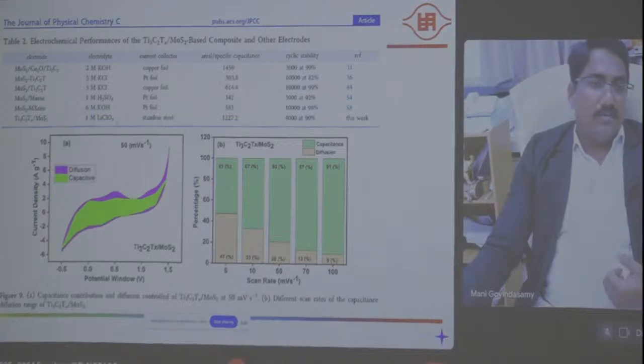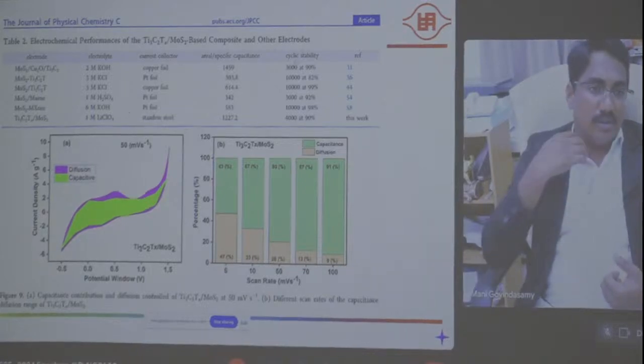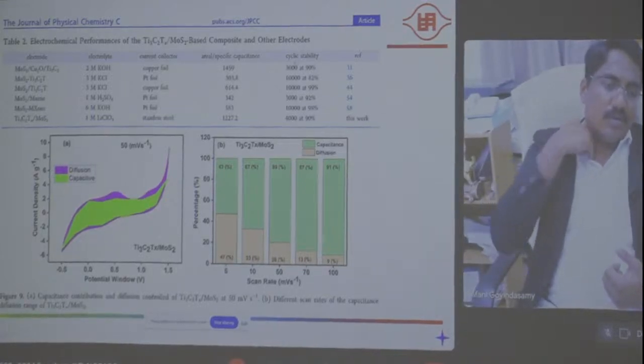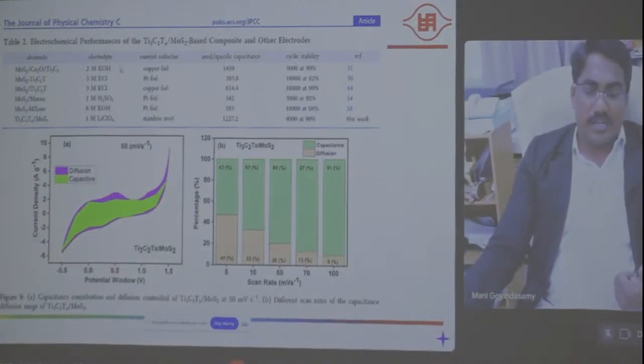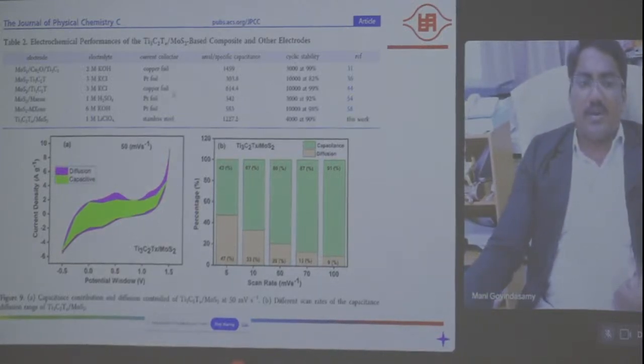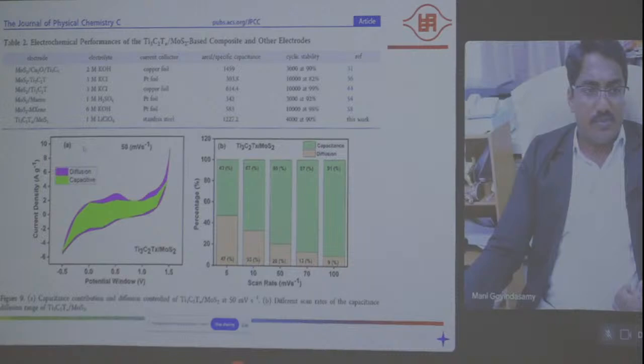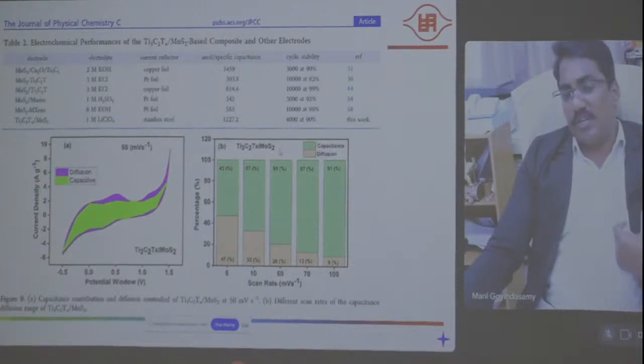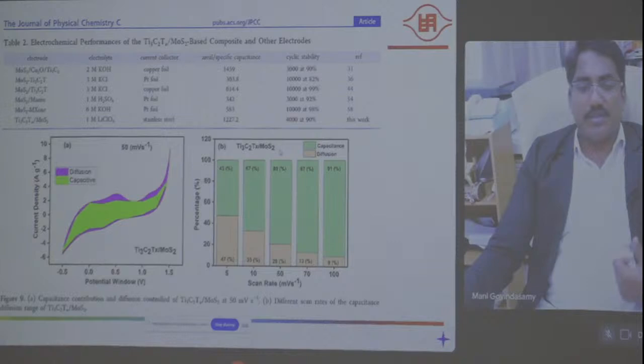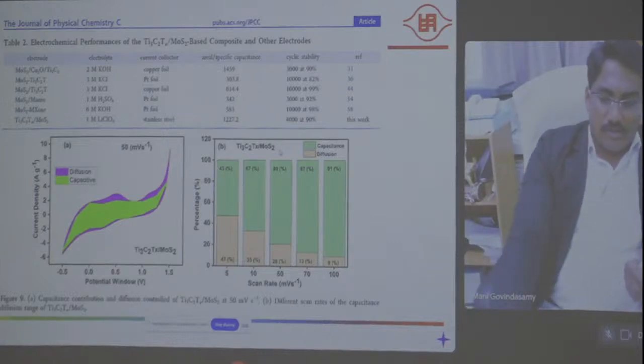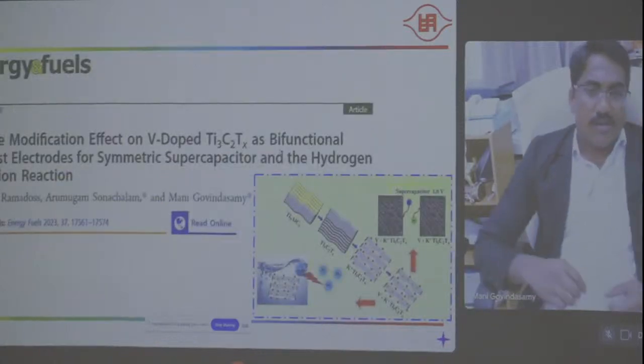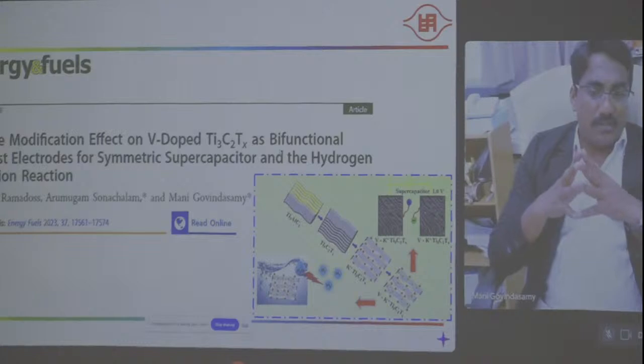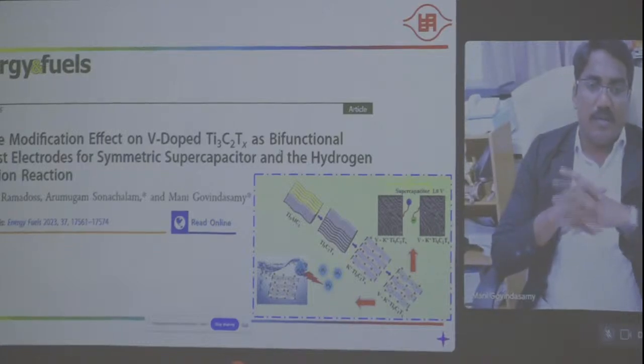In this work we used lithium perchlorate as the electrolyte. Later we developed KOH related electrolytes. We tried different electrolytes, but it was more stable in lithium perchlorate. So this one we used for supercapacitor applications. The second one we developed for doping, metal sulfide combined with the MXene.